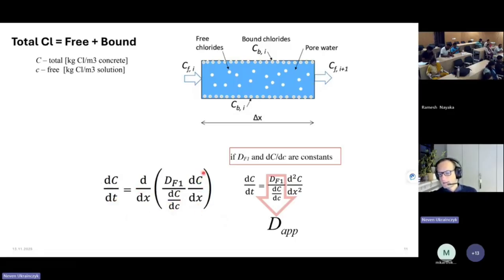I will explain this later. I'm just explaining the diffusion equation, how you derive it. So basically you have the concentration gradient. If you take the second derivative, which basically means the change of flux, so how many chlorides, the rate of penetration of chlorides, what comes in the steady state should be equal to what goes out. So this is exactly Laplace. The change of the flux is 0.